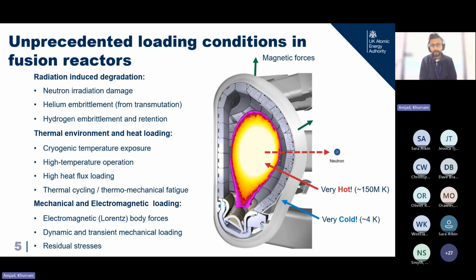And then when we talk about heat loading, I think within a few meters, we are talking about a significant temperature gradient. So from cryogenic at the outer shell, where we have a superconducting magnet operating at very cold temperature, to very hot temperatures in the middle of the vessel, where we have a burning plasma. So we are not just concerned about very high temperature, we are concerned about cryogenic temperature, we are concerned about temperature gradients, there are high heat flux loading, there is significant thermal cycling from start-stop of the device. There is a significant overlap with some of the conditions that we see in the aerospace or aviation sector as well.